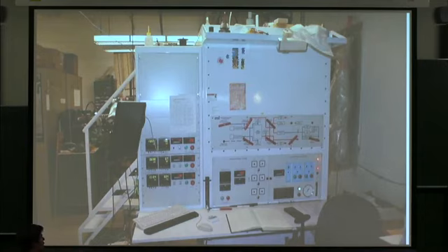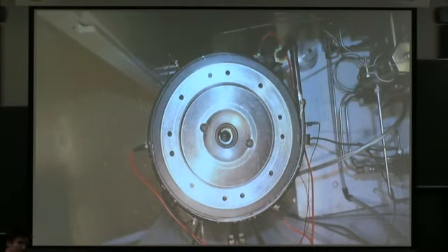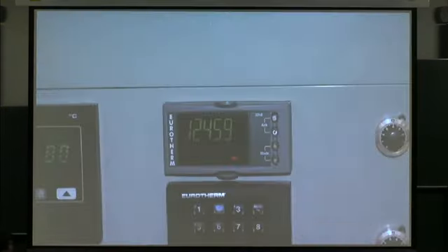And we'll move around to the back side. So here is looking inside the box. This is where the pressure vessel is. And we'll look down on top of it. And so there's a bore out of the center. You insert the assembly into that cavity. You can seal it, pump it full of argon gas. That provides a confining pressure. You can internally heat it. There's a furnace inside of this and other instrumentation. And so we tend to operate at about 1200, 1250 degrees C. There's a decimal point right there.